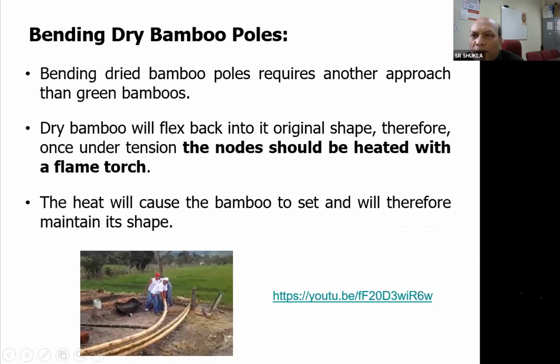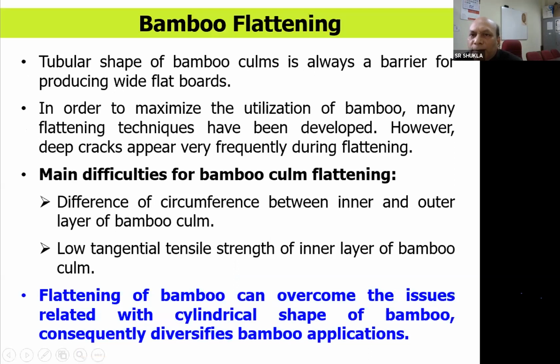Then bending the dry bamboo. Those were the green bamboos. Now dry bamboos can also be bent, but it requires a different approach compared to green bamboo. Dry bamboo will flex back into its original shape, because once under the tension, the node should be heated up with a flame or torch, and then the heat will cause the bamboo to set, and therefore it will maintain its shape. So when we want to straighten the dry bamboo, we have to heat up the node portion mainly.